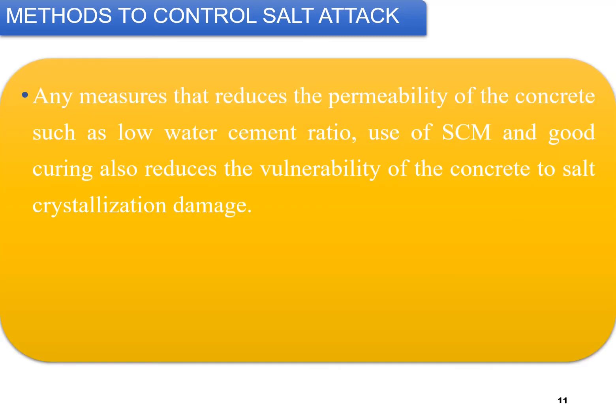Any measures that reduce the permeability of concrete, such as lower water-cement ratio, use of supplementary cementitious materials (SCMs) — which include mineral admixtures such as fly ash, silica fume, and GGBFS — will reduce vulnerability to salt crystallization. Good curing will also have a great impact in reducing the vulnerability of concrete to salt crystallization damage.